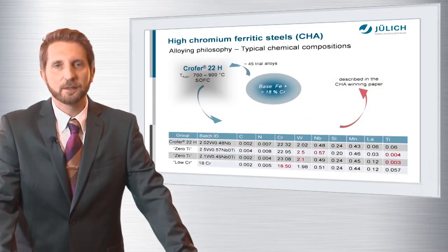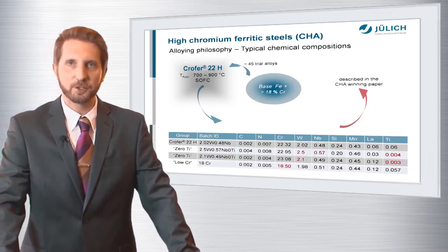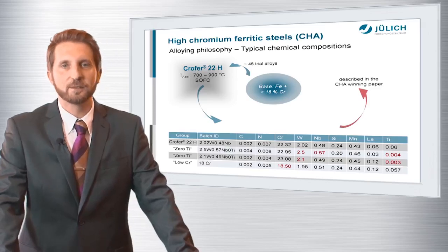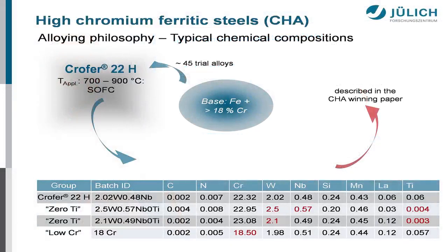So traditionally or historically, our steel development dates back to the development of the commercial grade Crofer 22 H, which is a 22 chromium ferritic stainless steel, which was designed at our institute together with VDM Metals in Germany. And originally this grade was developed for the application in high temperature solid oxide fuel cells for a temperature range of about 700 to 900 degrees C.